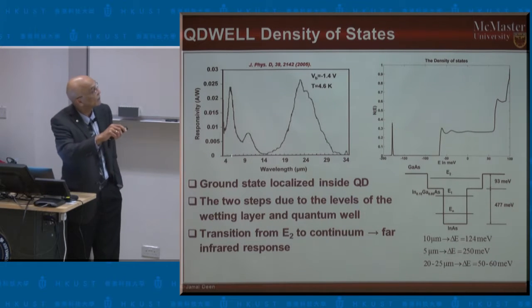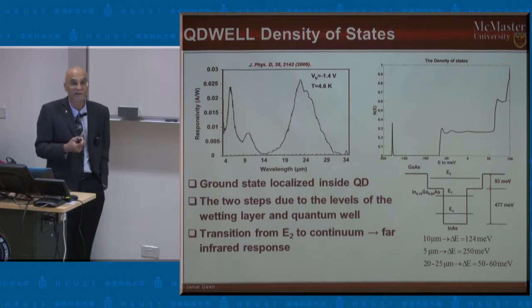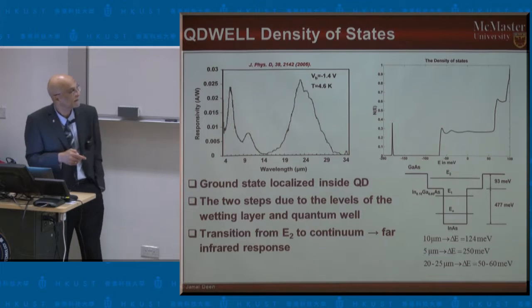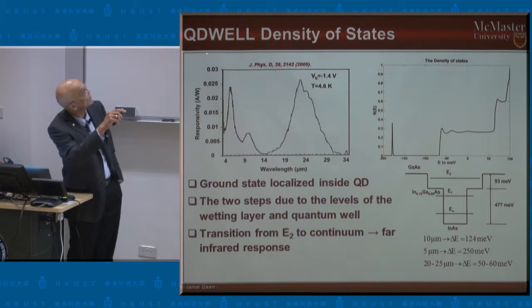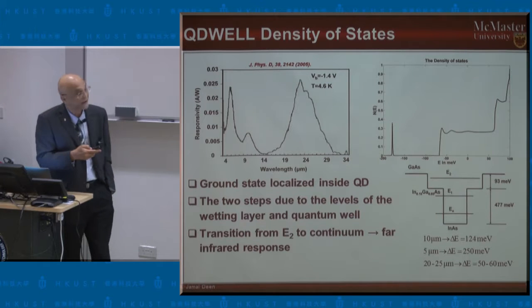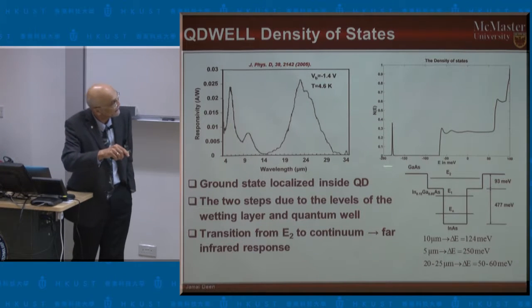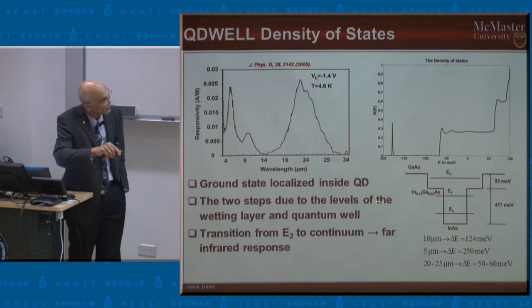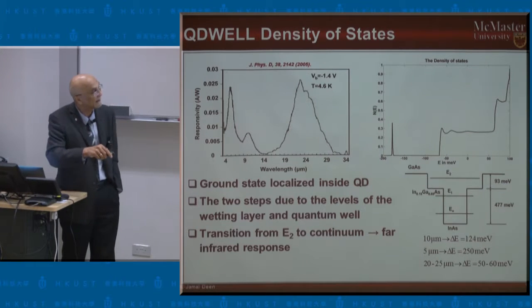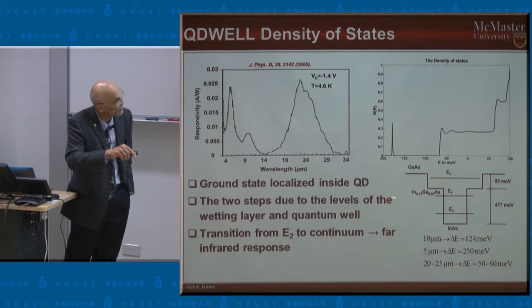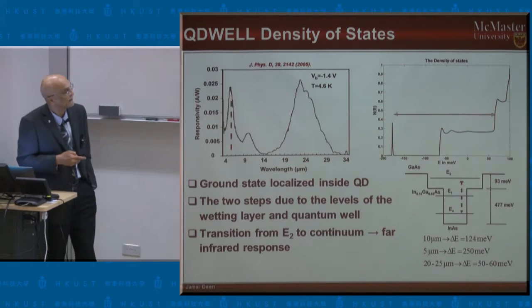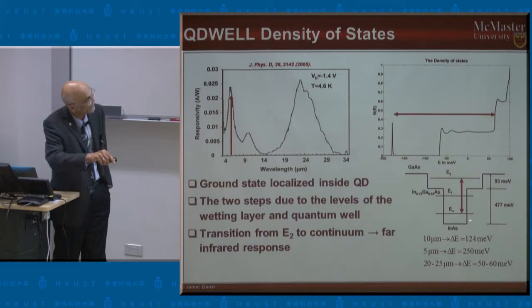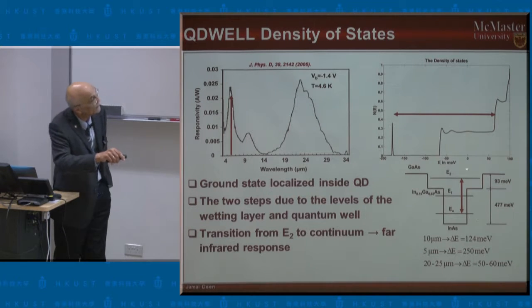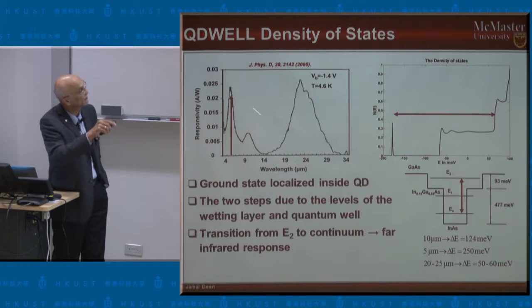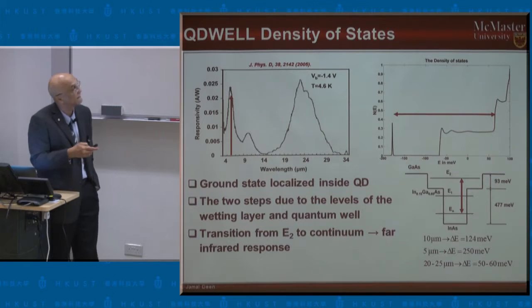So this is an example of the responsivity as a function of wavelength. And in the first instance, what we're interested in doing is looking at where these peaks come from. What is physically responsible for such peaks in the quantum dot structure. So this is a quantum dot in a well. In such a case, we can actually calculate the density of states as a function of energy. We can look at the localized states within the quantum well and in the wetting layer. So here we have 3 states, E0, E1, and E2. And if you look at these states, we can see that the transition from E0 to E2 is responsible for this first peak, and this corresponds to this transition here.